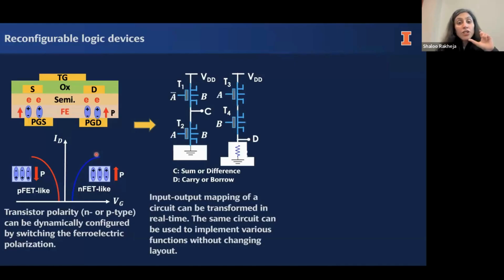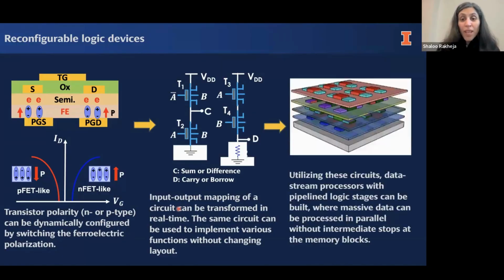So it's electrostatic doping, which is why we can control this. So now if we change the functionality of one transistor from N-type to P-type, what we can do is the same circuit can implement either a subtractor or an adder. We don't have to change the layout of anything. We just have to change the voltage on the programming gate. We have two programming gates on the bottom. And so what we've shown is that we have some work where we've shown that these can be really helpful for data stream processors, and we can do a lot of parallel processing on massive data for these devices.